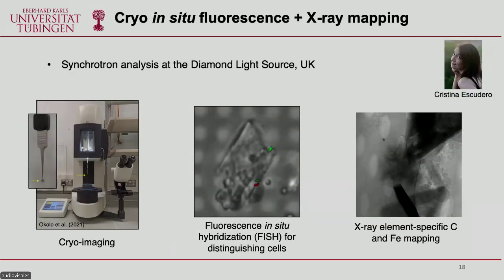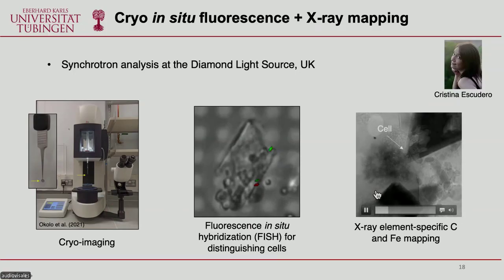So for example, we also tried a different technique. This is called the cryo in situ fluorescence coupled to X-ray mapping. This is something that we are developing together with Cristina Escudero, my collaborator. And we went to the Diamond Light Source in order to do high resolution imaging. What's cool about this technique is that you can do cryo imaging, which means minimal sample preparation. We can couple this to fluorescence in situ hybridization. Then we can tell apart which ones are the iron reducing bacteria, which ones are the iron oxidizing bacteria. And then we can do 3D mapping for X-rays, element-specific carbon and iron.